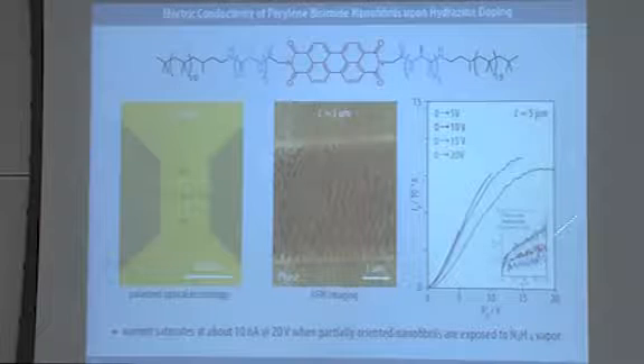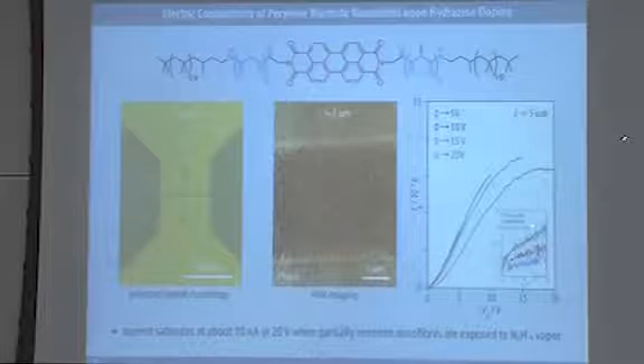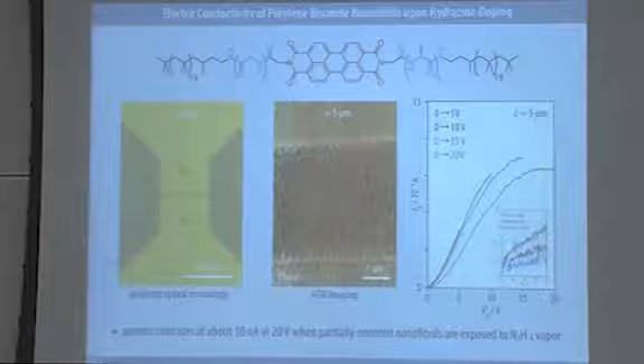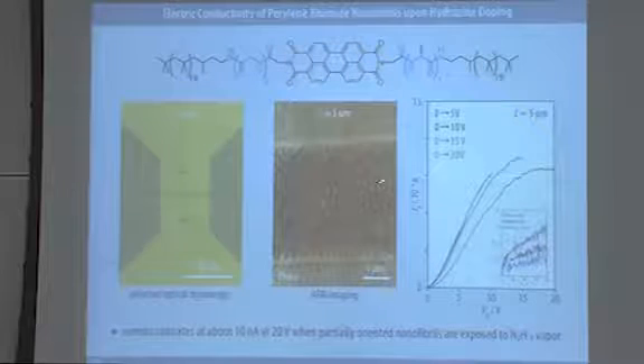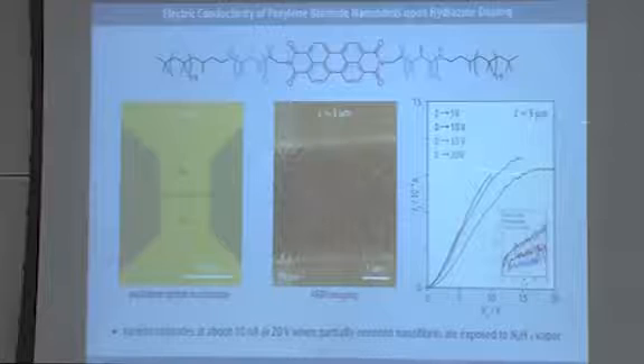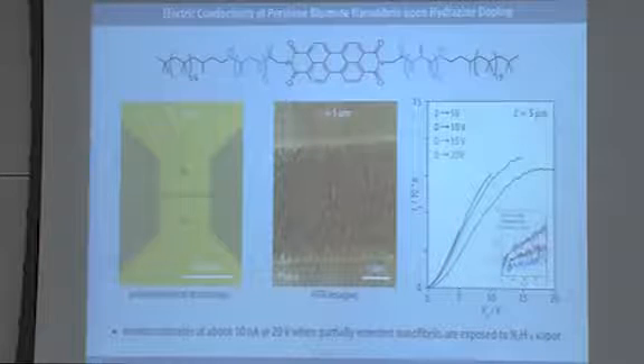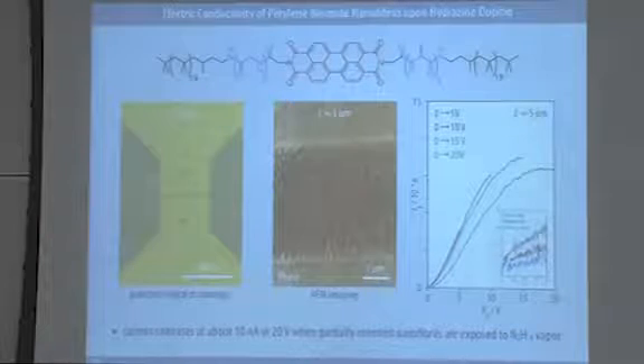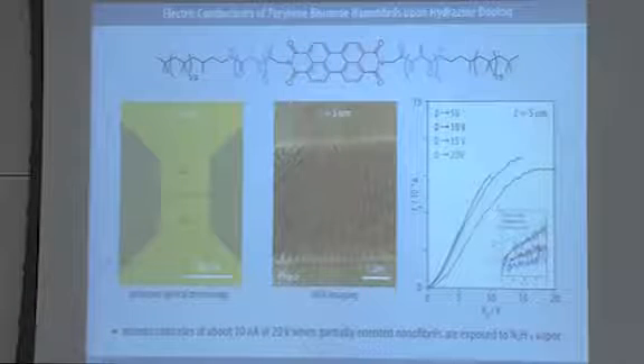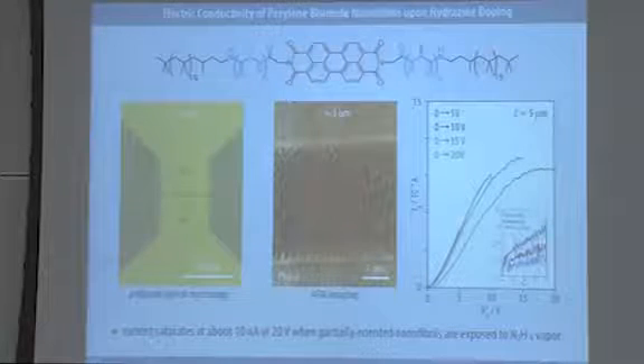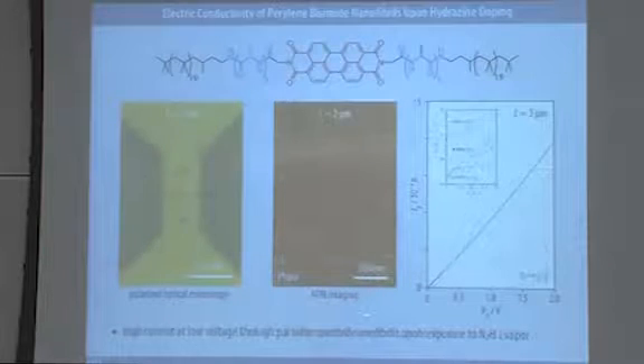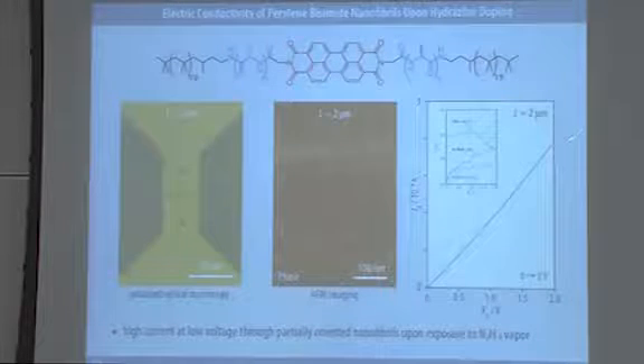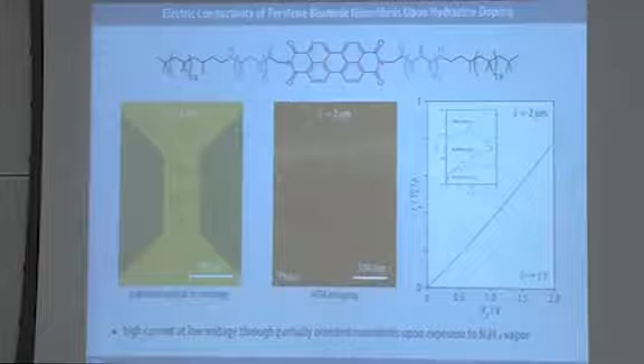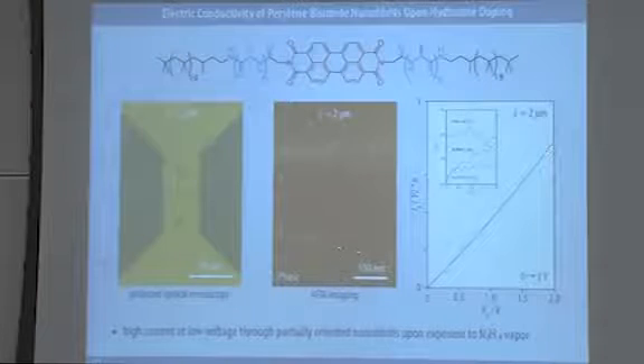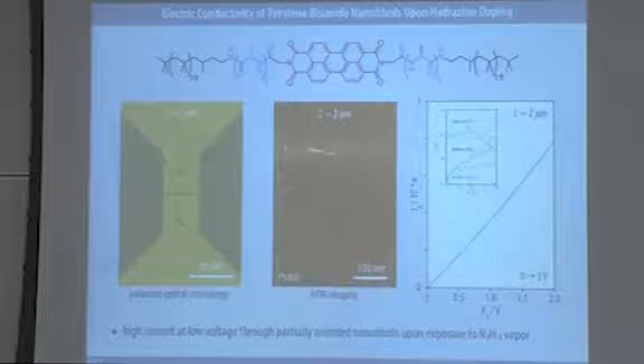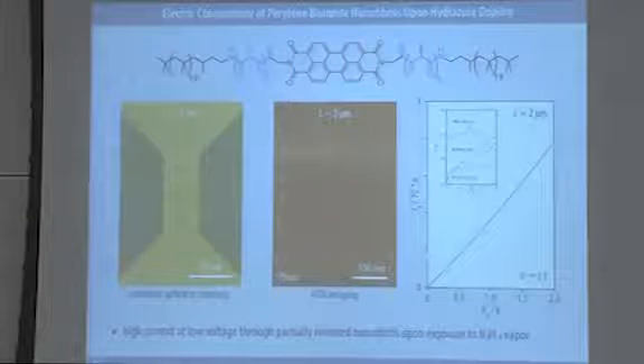But as soon as we expose the system to hydrazine vapor, we actually get decent current voltage curves, which in the case of the 5 micrometer device seem to level off at about 10 nanoampere for 20 volts source drain voltage. The 2 micrometer device shows an almost contact resistance free current, but in this case we have to work on this experiment a little further because we're not entirely sure that there is not gold actually spanning the channel. We need to make sure that it isn't.